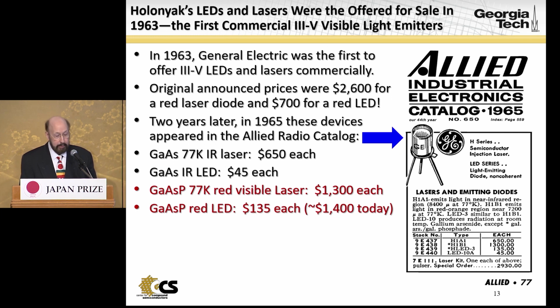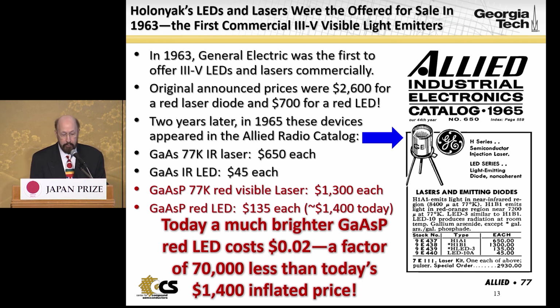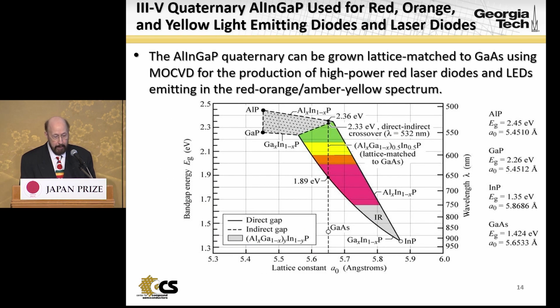A gallium arsenide IR LED was $45 a piece, and the laser diode was $650 a piece. The gallium arsenide phosphide red laser diode was deemed to be twice as valuable, so its cost was $1,300 each, and the gallium arsenide phosphide red LED was $135 each. If you translate that to today's dollars, each LED would cost you $1,400. So imagine having a sign somewhere with that kind of component in it. Today, a much brighter gallium arsenide phosphide red LED costs about 2 cents in today's dollars, a factor of 70,000 less than today's $1,400 inflated price. So dramatic reductions in cost and improvement in performance.